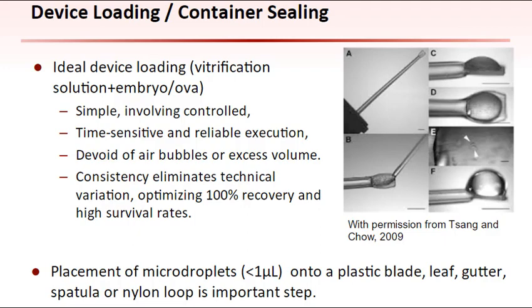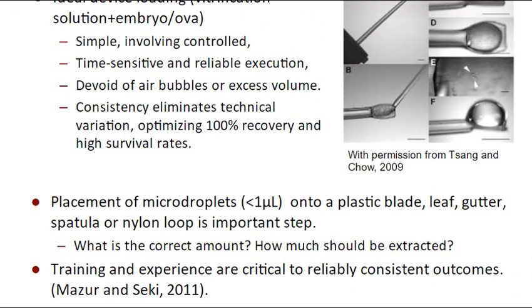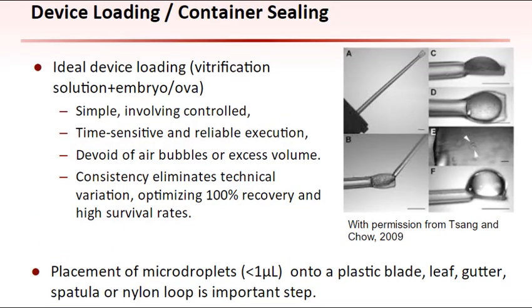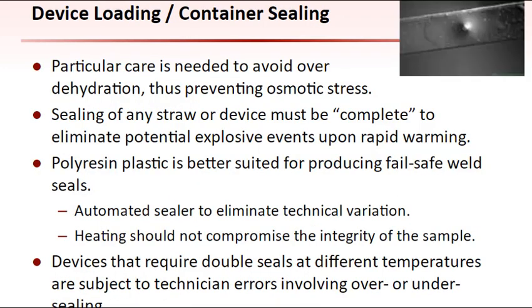Training and experience are critical to reducing technical variation and reliably consistent outcomes. The drive to attain super-rapid cooling rates greater than 50,000 degrees Celsius per minute through maximal extraction of vitrification solution comes at a risk of osmotic injury and reduced tolerance of the device to slower warming rates. After the material is placed on the device surface, the excess volume can be pipetted off. When extracting residual vitrification solution, care must be taken to: 1. not pipette an embryo or egg accidentally, 2. not remove too much volume causing excessive dehydration or injury, and 3. not take too much time, being overly precise.